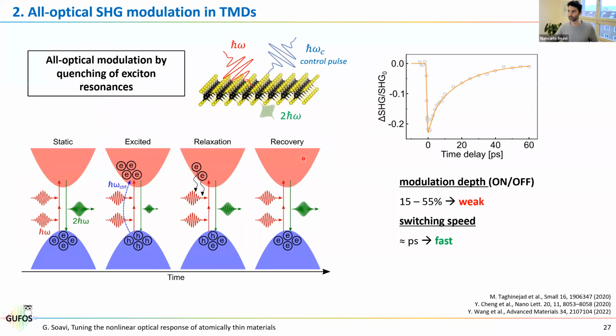There is a second approach that is very similar to what we were discussing already for graphene. So you have h bar omega 0, you have a control pulse. The control pulse generates electrons in the conduction band. You will quench your exciton resonance, and by doing that, you will reduce the second harmonic efficiency. So again, for negative delays, you have a constant response, then you have a drop in the second harmonic at 0 delay, and then this recombination time is the typical recombination time of the excited state in these 2D semiconductors.